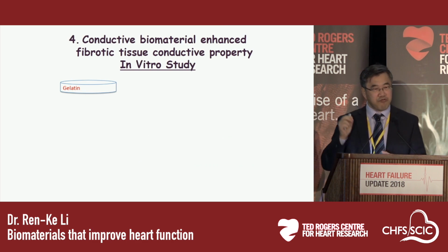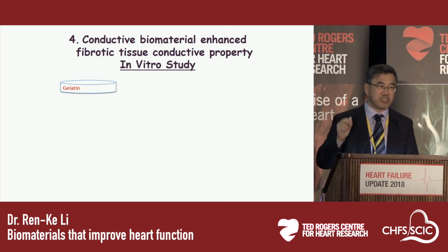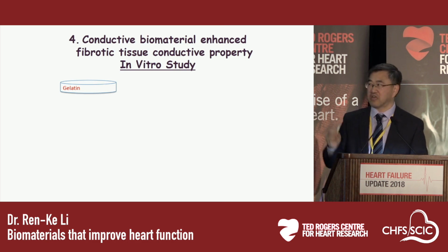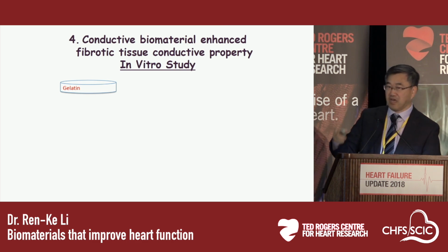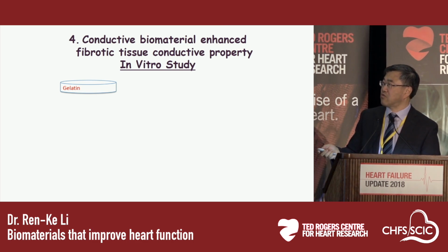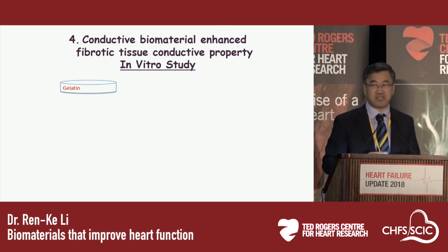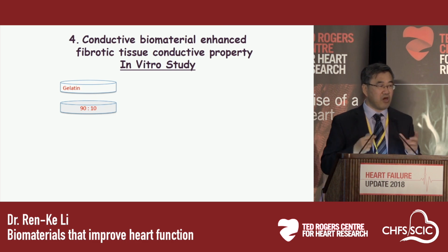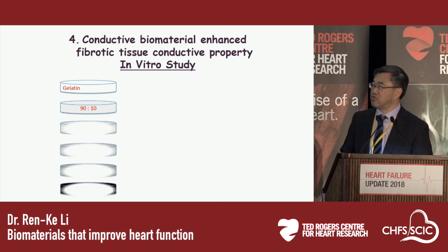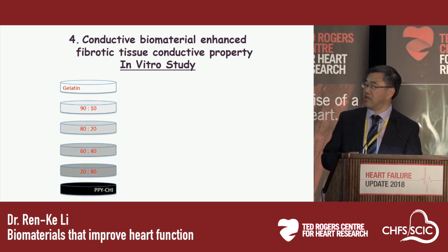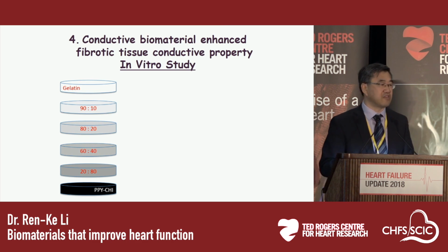We want to know if we add the conductive biomaterial into the matrix, whether that will change the extracellular matrix conduction or not. So my student, Daniel, sitting there, created this extracellular matrix. We use gelatin to create the extracellular matrix. And then we created multiple different compositions mixed with the conductive biomaterial: 9 to 1, 8 to 2, 6 to 4, 2 to 8, and then pure conductive biomaterial.